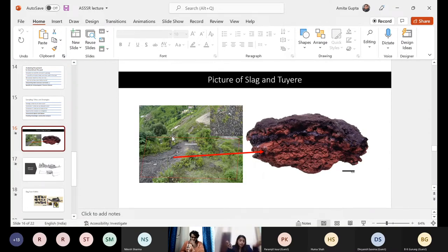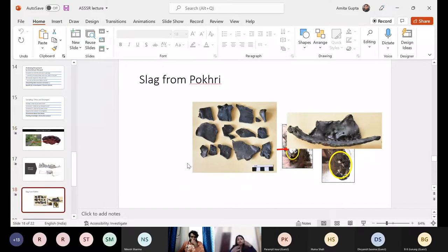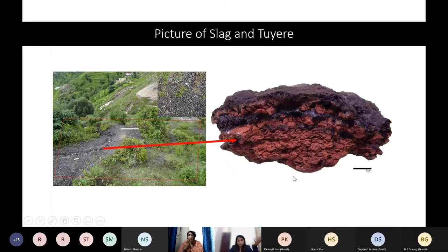And there are the smelting processes which the past smelters were doing. They were cleaning the ore, then roasting the ore, then putting it into the furnace, and at a particular temperature, like 1400 degrees, the copper or iron is smelted. They needed to wait at least one night to get the melted metal. Then the rest is the slag, because they don't want to waste the metal in the slag. So in this technology, what they were doing was crushing the slag to get more and more metal prills. Just wait.